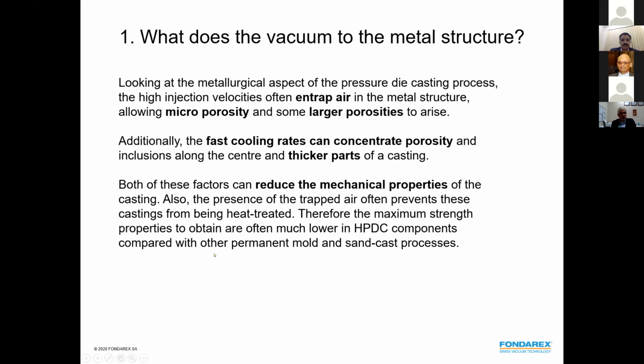Yeah. So to start, of course, why do we have metallurgical problems in pressure die casting? As everybody knows, low pressure gravity casting in most times has better structures than aluminum pressure die casting. Mainly it is because of the fast filling, where it entraps some air and therefore microporosity shows up, and in many cases also larger porosity comes up. And then of course also through the fast cooling rate, we create some shrinkage porosity, micro shrinkage porosity. It's kind of complex, happening during the solidification with everything we have entrapped into the alloys.